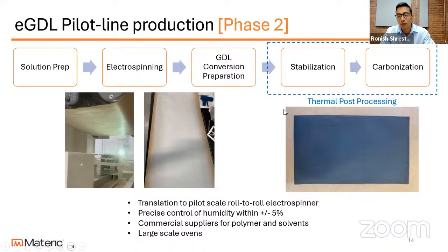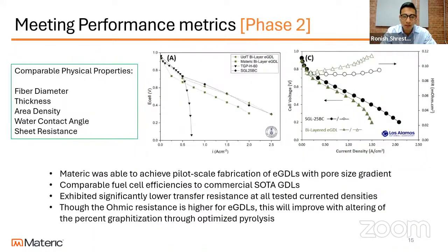So we had to inquire and set up ovens and furnaces that were capable of handling these large rolls of material and thermally process them into the final carbon nanofiber mats. So this entire process, I think we spent about a year or slightly more than a year in electrospinning, trying to get the mat that was suitable to their needs. We were continuously providing the samples that we produced on our roll-to-roll system for their testing to compare and optimize it to produce a type of material that they saw with their lab scale method.